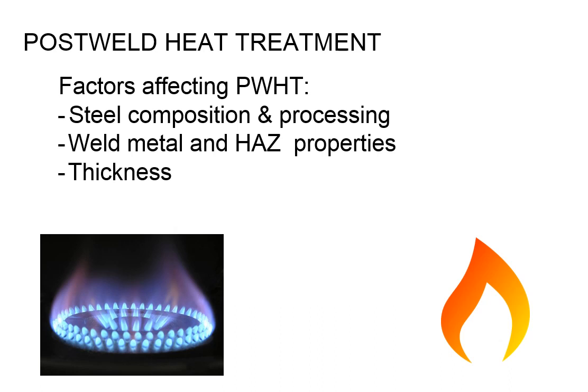These are the 3 biggies. Steel composition and processing. What is the chemistry? You've got to look at the chemistry of what's being post-weld heat treated and how it was processed. Quenched and tempered or something. Are you going to mess it up if you post-weld heat treat it? Or if you post-weld heat treat it too long, are you going to turn it into absolute mush? You're going to take a material that was supposed to have a certain hardness and you're going to cook that hardness out of it, basically anneal it.